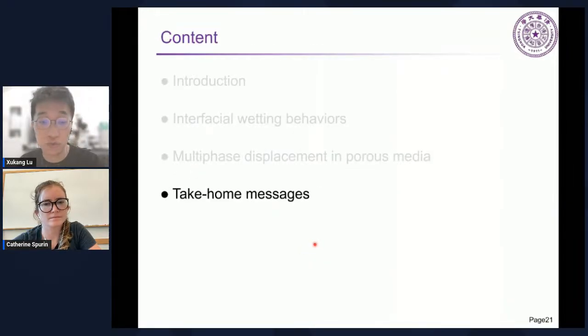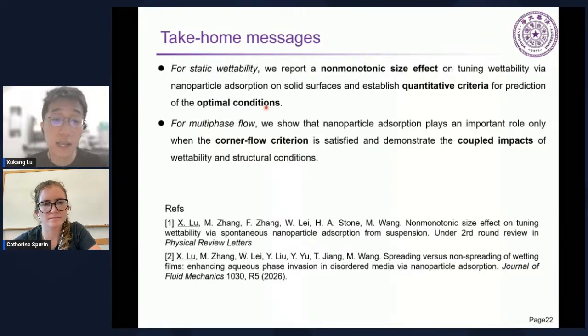And finally, our two take-home messages. For static wettability, we report a non-monotonic size effect on tuning wettability and establish quantitative criteria for prediction of all the optimal conditions. And for multiphase flow, we show that nanoparticle adsorption plays an important role only when the corner flow criterion is satisfied, and demonstrate the coupled impacts of both wettability and structure conditions. So here are some corresponding manuscripts and papers. The multiphase flow part has been published in JFM.